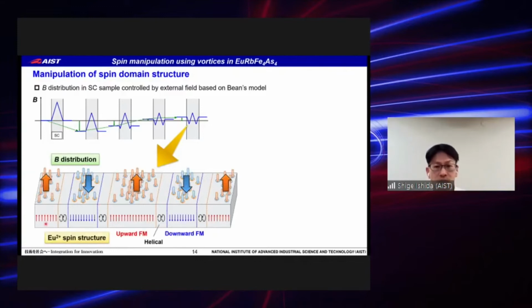Based on our model, europium moments align ferromagnetically upward or downward depending on the direction of the vortices, and the helical order appears around the domain boundaries where the vortex density is close to zero.